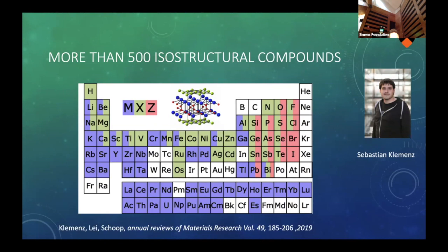And so, of course, we could argue that we just need to count the electrons to know where the Fermi level is. However, for this, we need to know about oxidation states, and these can be very ambiguous in intermetallic compounds. So just simple electron counting is not necessarily a good tool to filter out the good materials from the ones which are not interesting.